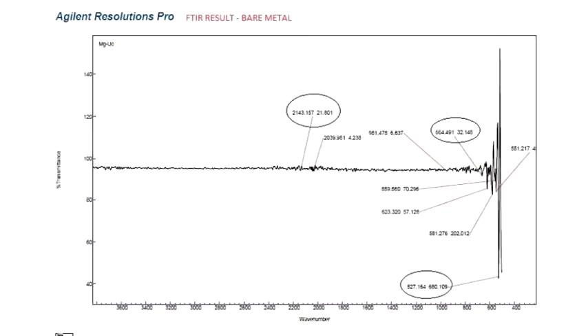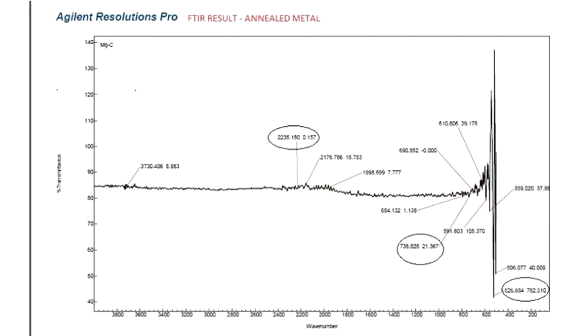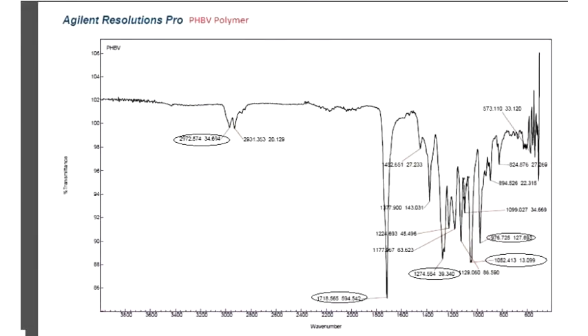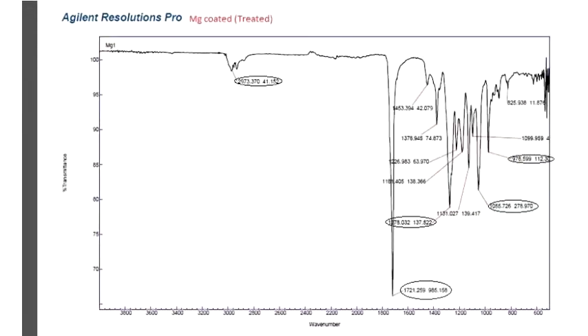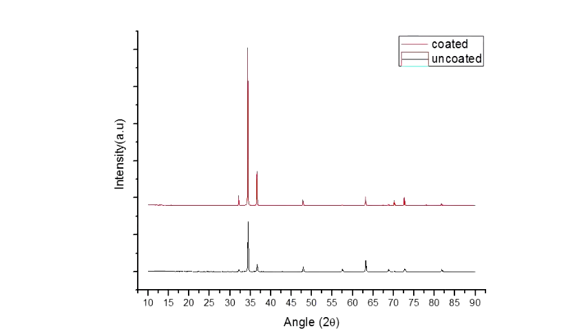Next, coming to the FTIR analysis, that is Fourier transform infrared spectroscopy, the pattern of the annealed and coated metal is similar to that of the bare metal, whereas the pattern of the annealed, coated and treated metal is similar to that of the PHBV polymer. This signifies that the PHBV polymer has been coated uniformly as well as present all over the surface of the substrate, that is Mg alloy AZ31. Next, coming to the XRD analysis, the peaks at 30 to 40 degrees 2 theta have been amplified in the coated metal. This is because the XRD peaks of the PHBV polymer lie in the same region, so the peaks have been amplified compared to the bare metal, and this has been proved previously by Wang et al.